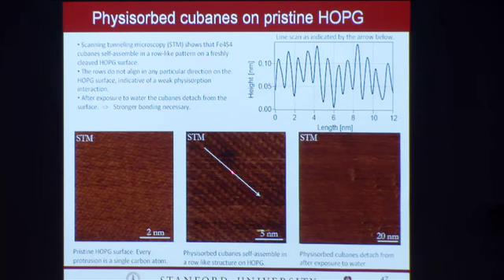So very quickly, this is our highly oriented pyrolytic graphite surface where we deposit our cubanes on. You can actually see this is atomic resolution on the HOPG. When we drop our cubanes on there, we form a self-assembled monolayer in DMF, where we can do a line scan and show that the width of these molecules, they're standing shoulder to shoulder. They're exactly 1 nanometer apart, which is exactly what you'd expect them to be. But then we immerse this electrode in water, and they desorb off.